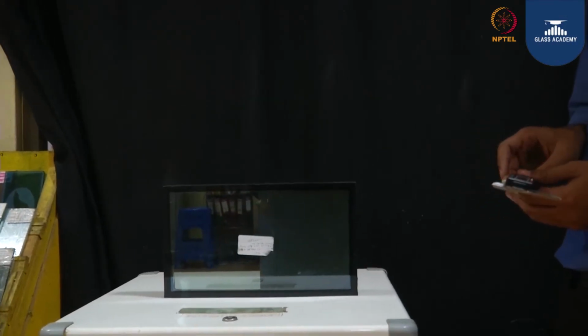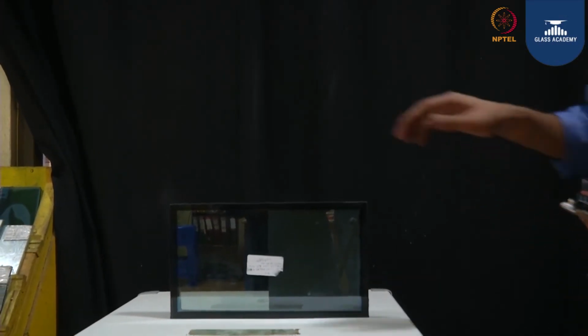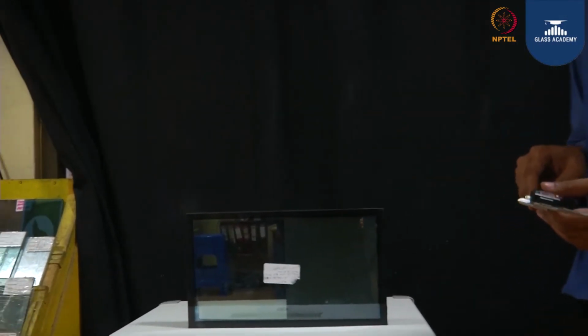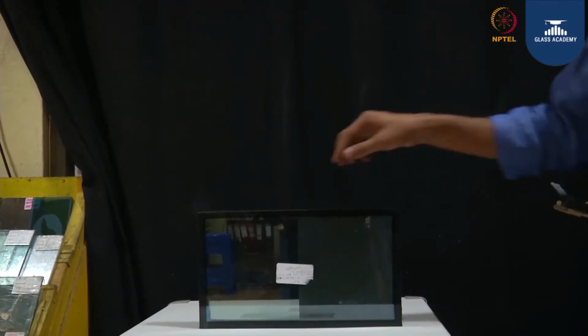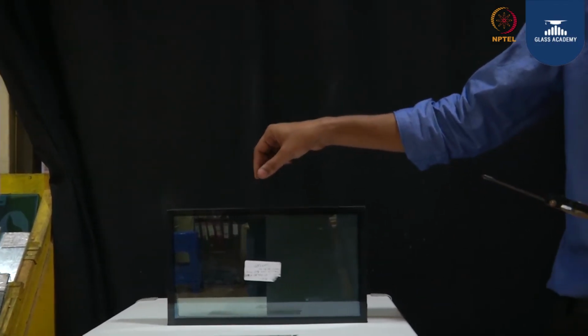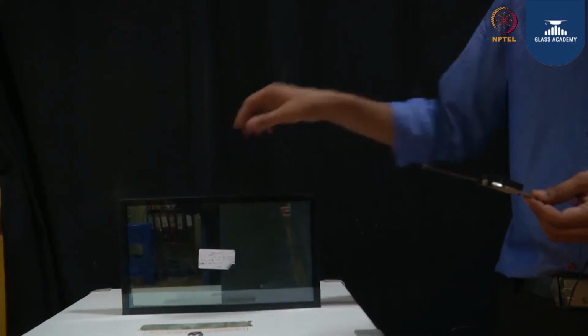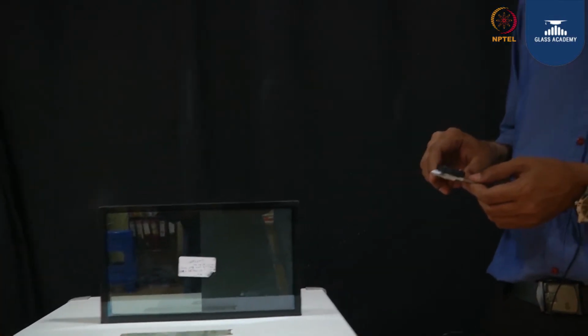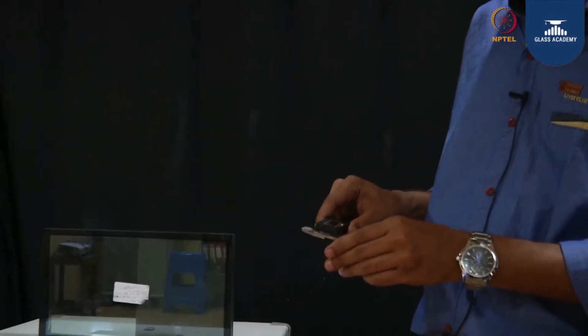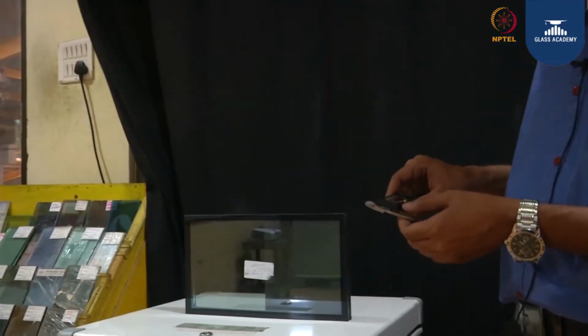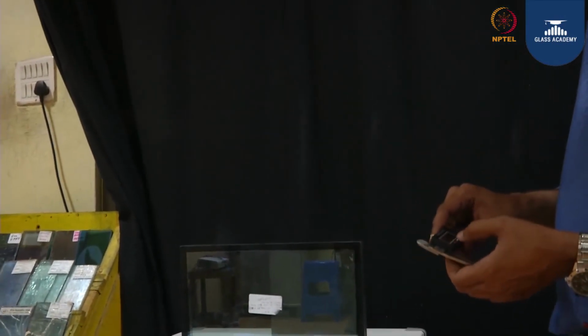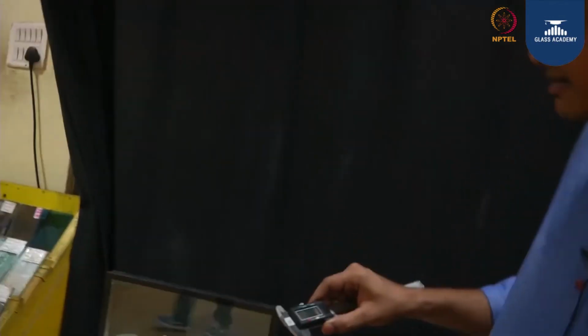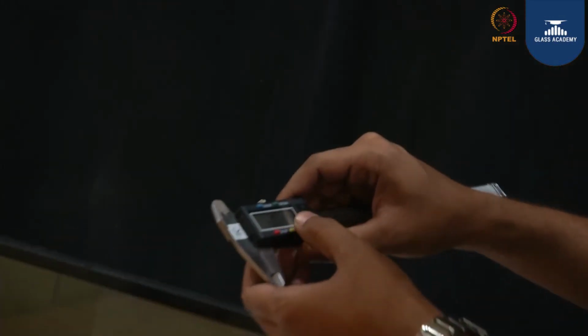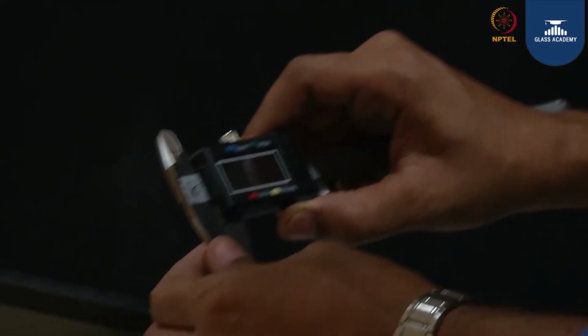Now we are going to see one more test related to the final DGU product, known as the parallelism test. As the DGU is a composition of two glasses with an airspace in between, we need to measure the overall thickness of the glass, because the glass can be heat strengthened, toughened, or annealed, and there is also an air gap in between.